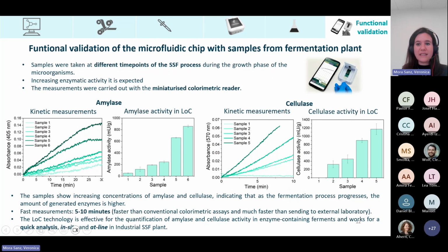The reader makes kinetic measurements. It measures absorbance in function of the time. We can see both results for amylase and cellulase. Here we can see that as the fermentation process progresses, the slope of these kinetic measurements also are higher for amylase and also for cellulase.